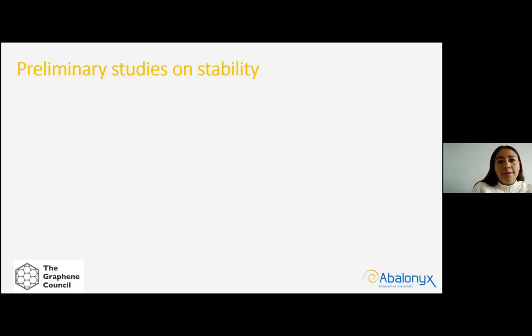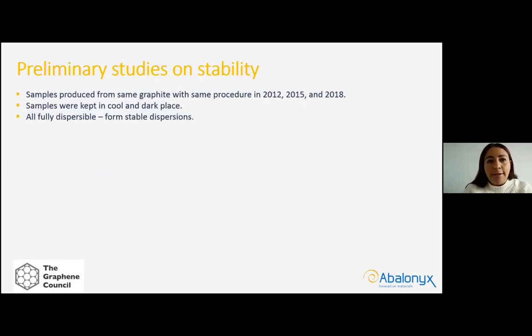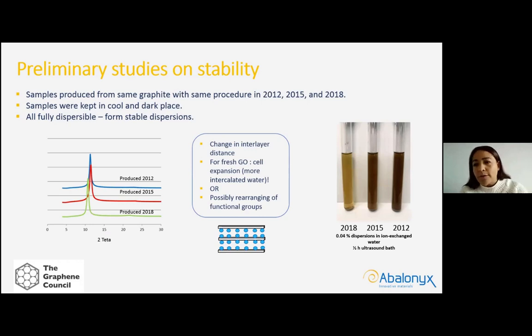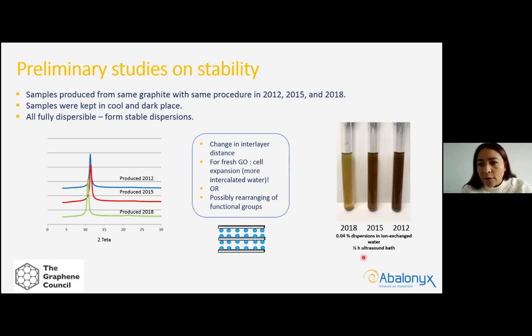So what we did was to start some preliminary studies in stability. We took 3 samples that we had in storage from 2012, 2015, and 2018 that we knew were kept in a cool and dark place, and made stable dispersions from these materials. And these are the results, the preliminary ones. To the naked eye, it is very easy to see that something is happening. Let me see if I can get the pointer. Here. So to the naked eye, it is very easy to see that there are changes happening in the material. And we suspect that it's some kind of reduction.